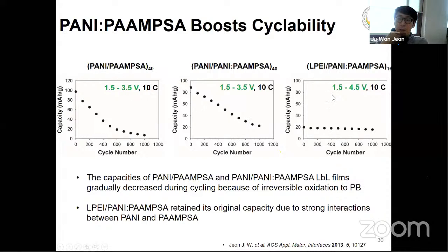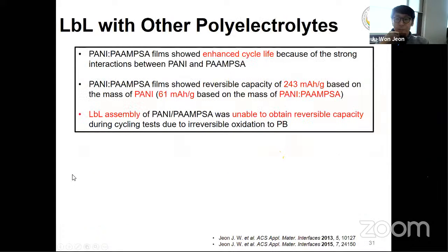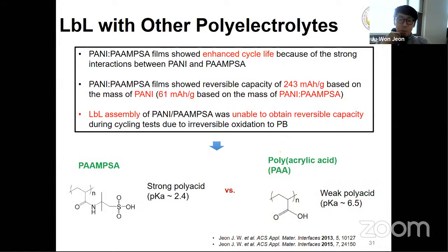And then this LPEI/PANI:PAAMPSA shows the highest electrochemical stability. So it just showed very stable electrochemical property during the cycling, but its capacity itself is not really high. So we thought, okay, how about another polyelectrolyte instead of the PAAMPSA? So we performed the layer-by-layer assembly using a different